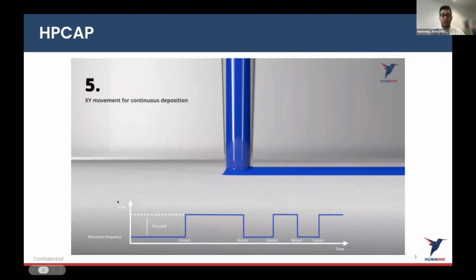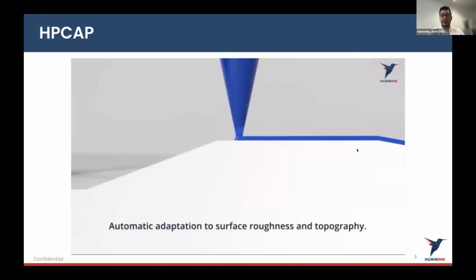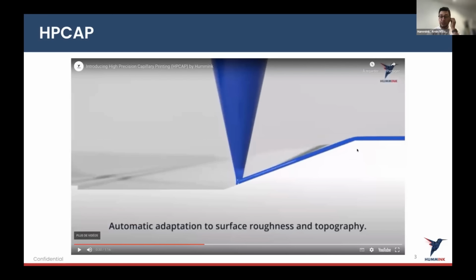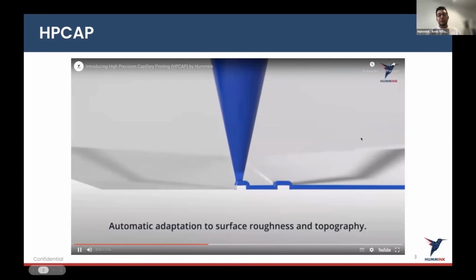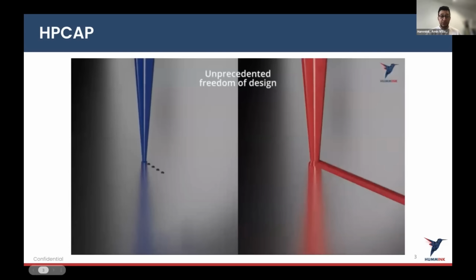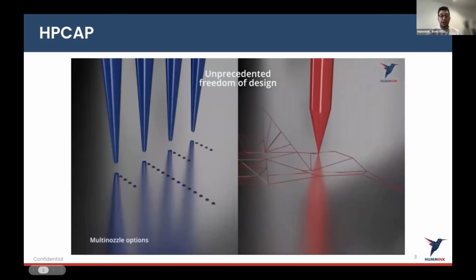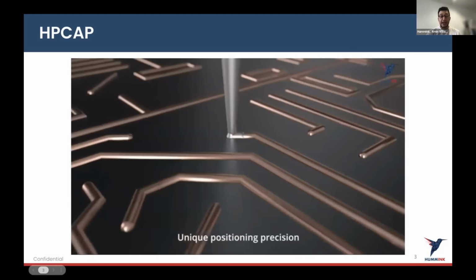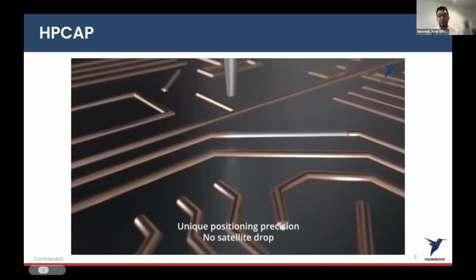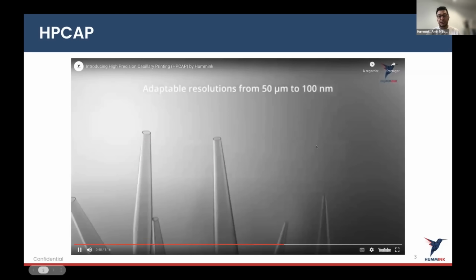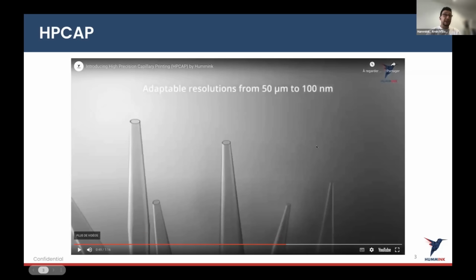We move the substrate below the tip, and we are able to constantly sense the substrate, so it adapts to the surface roughness and topography of the sample, because, like a blind person's cane, we are always sensing the surface to know where exactly it is. You can use a wide range of inks. We're working on multi-nozzle options, with huge freedom of design. It has 20 nanometer precision and doesn't generate satellite drops, so it's very efficient for repairing circuits that have defects, or for printed circuits in general.